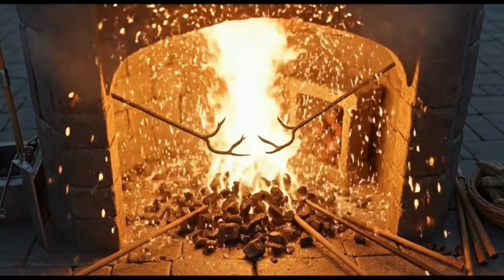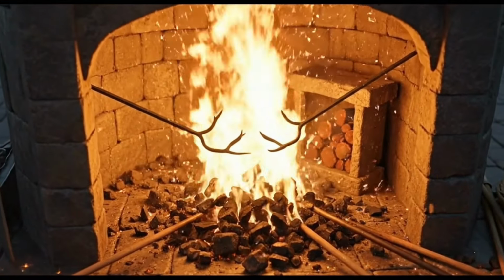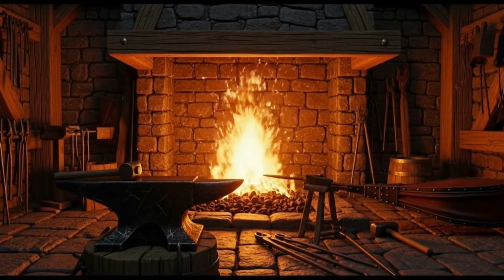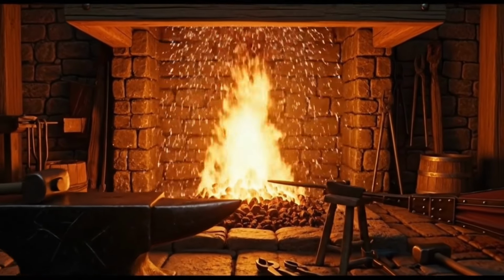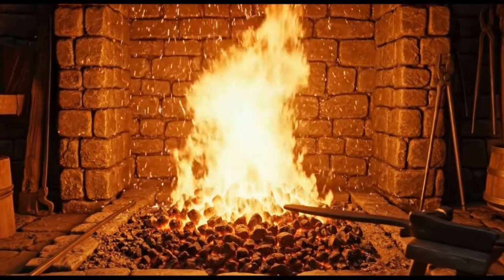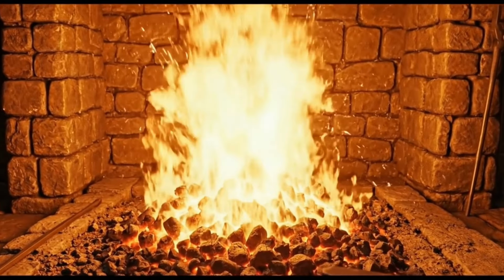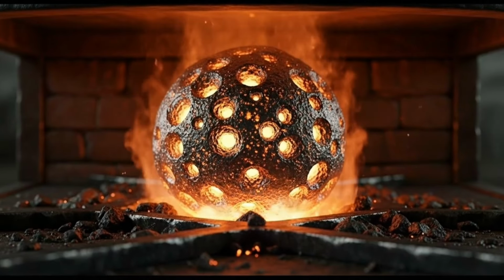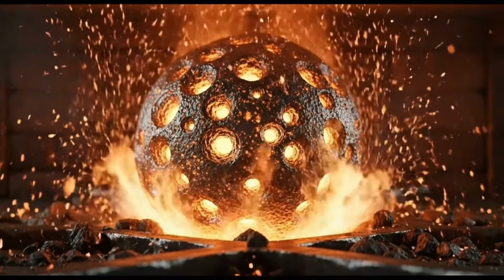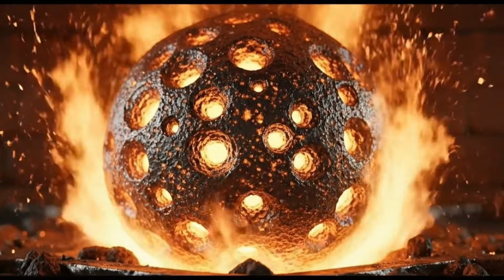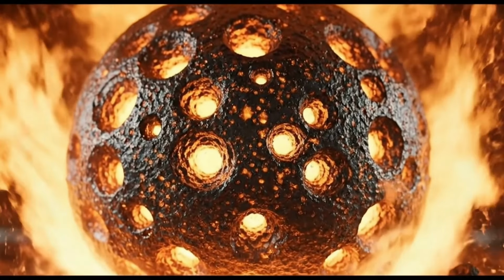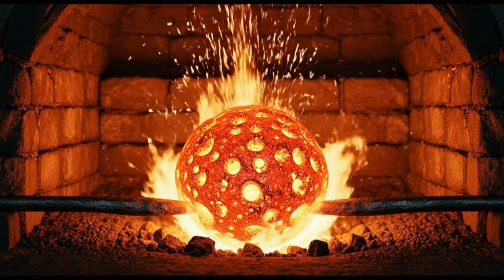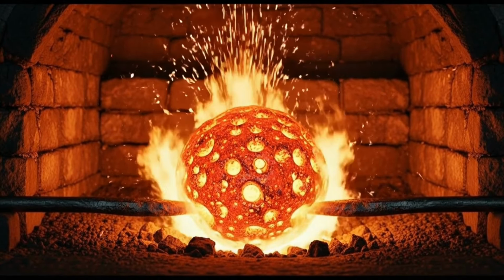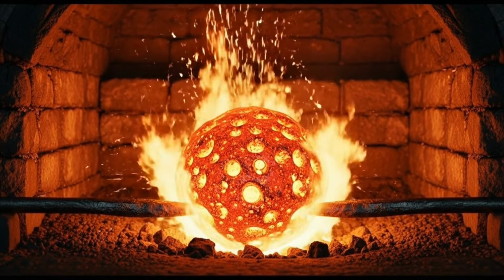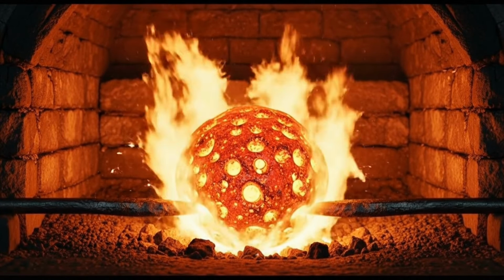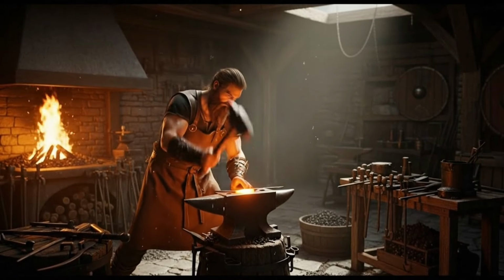At the same time, the empty rock contained in ore melted, forming liquid slag. This slag flowed to chamber bottoms and was removed through special openings. It carried away most harmful contaminants, purifying future iron. Reduced iron particles settled in chambers, fusing together into single porous masses. The entire smelting procedure could take from multiple hours to a full day depending on chamber size and ore quality. All this time, several people had to work bellows non-stop and add fuel.